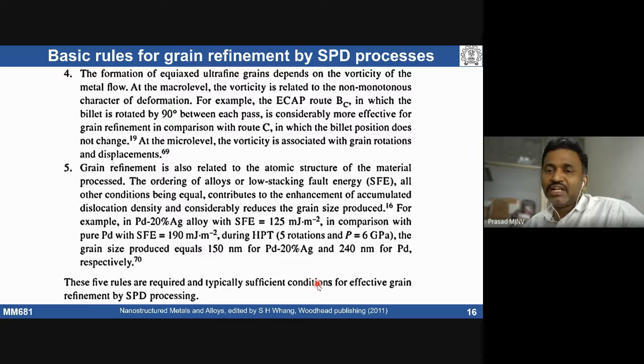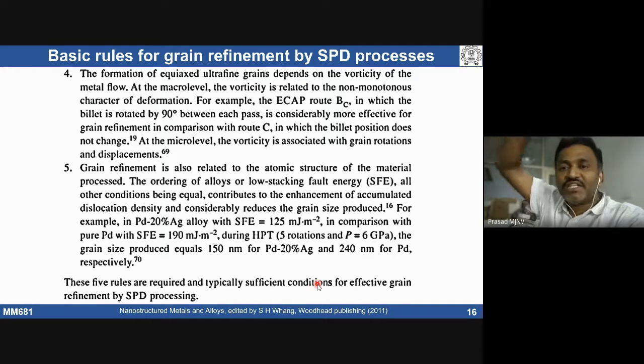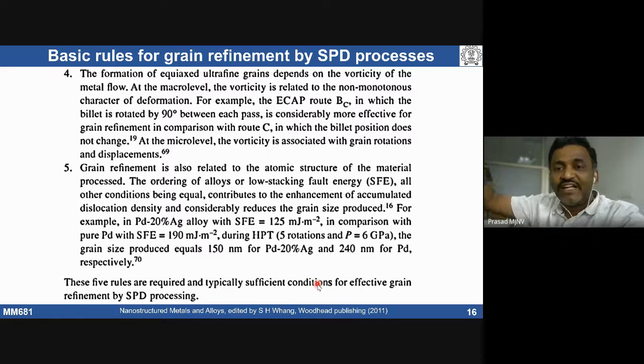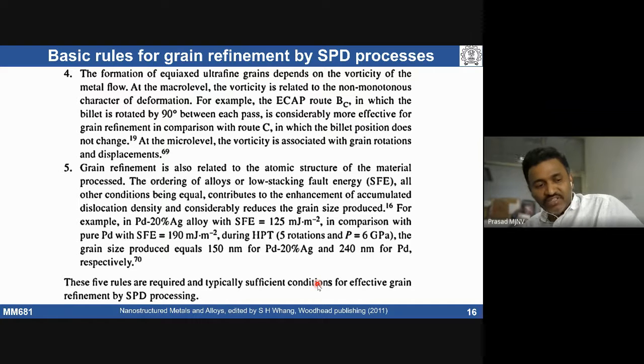I think in Russia a lot of effort is going into increasing the scalability of this process. They came up with big sheets that can also be subjected to ECAP. The only thing is we need a bigger, high-capacity press. There are limitations because we always have constraints. If you want to do bigger samples, I need a bigger die which can withstand those pressures, and a huge press. So these are the constraints and challenges associated with severe plastic deformation. People have nicely demonstrated grain refinement in lab-scale samples, but scaling up is the major issue with all these processes.